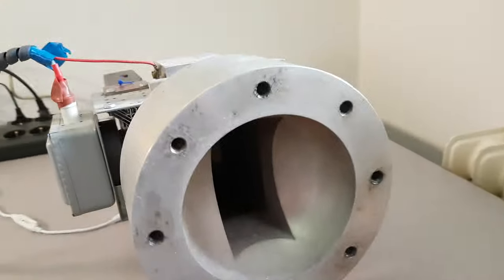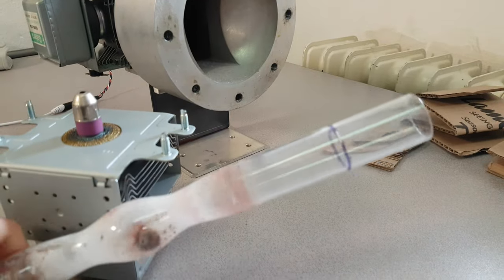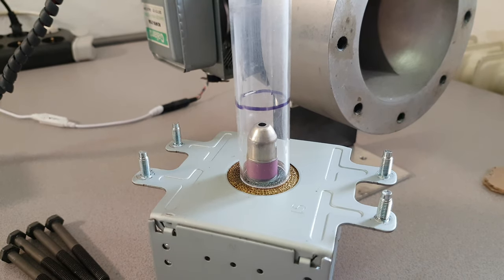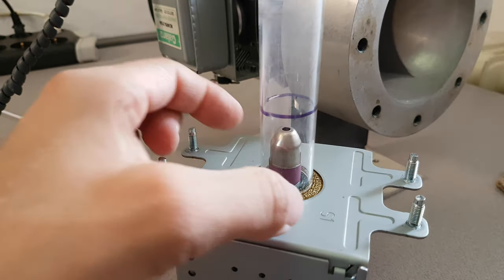If you look at the head and compare it to the inside of the reactor, you can see in there that it has this damaged head. The maker of the Supernova said that you can avoid this to some extent by placing some fused quartz or borosilicate over the head. So what I'm going to do is use this old tube here that was used in another Nova reactor — I've marked off the width of the waveguide — and I'm going to cut that with a high-speed drill to go over the tube at the end here to protect it, and hopefully that will prevent this from happening again.